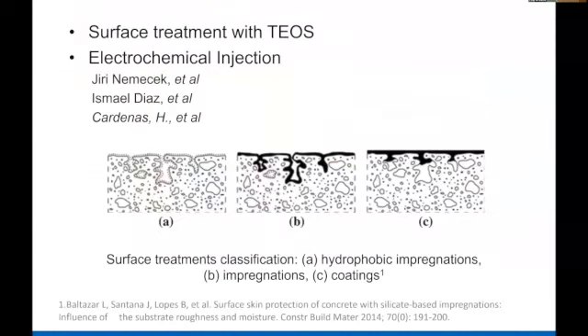And then another last example I want to give of using nanosilica is in surface treatment. We know that most of the damage, durability, corrosion of rebar starts at the surface. So if we can make the surface impermeable so that water and other ions cannot go in, that would be very good. So currently, there are 3 ways you can do it. You can use silane, which is hydrophobic, or you can use epoxy coating, as shown in C, or you can infiltrate it with mineral particle, most common being water glass or sodium silicate.